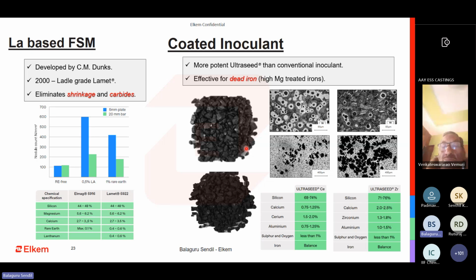Again, we have coated inoculants. Basically, this coating is with sulfur and oxygen. Why do we have it? When we see the metal which is treated with higher amounts of magnesium, it is dead. It is fully carbidic in nature. Your sulfur is completely lost. You need to have sulfur to make sure that nuclei grow to a respectable shape and size.